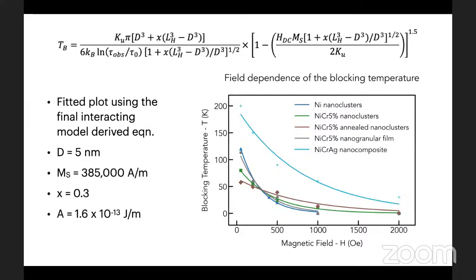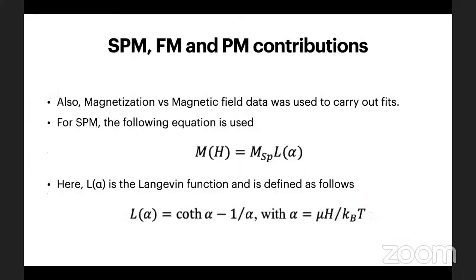In fitting, we use certain machine learning to re-verify whether our final fit indeed replicates our original data. So now, before talking about the final results, I would like to mention that we also measured several magnetic components of our samples at above and below blocking temperatures. Here, MH data was utilized and SPM, FM, and PM equations were carefully studied by referring to various other papers. For SPM, we have used the Langevin function, which is defined as follows.